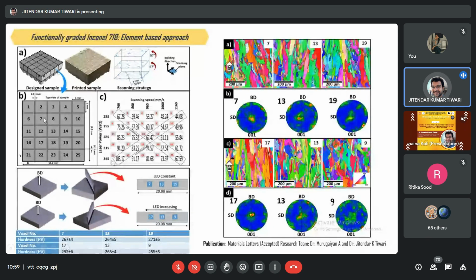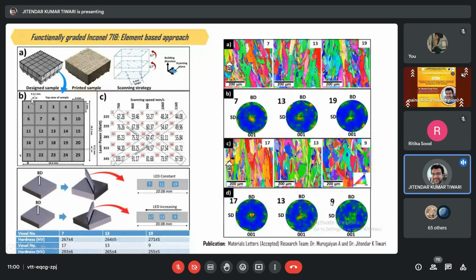So basically, as you can see, this is a voxel based approach. This work was already published in Materials Letters, but I just want to emphasize a little bit more about it, that we divided the already printed sample in voxel form. Each voxel has a different laser energy density. Laser energy density, in simple terms, is the amount of energy which we give for fusing the material.